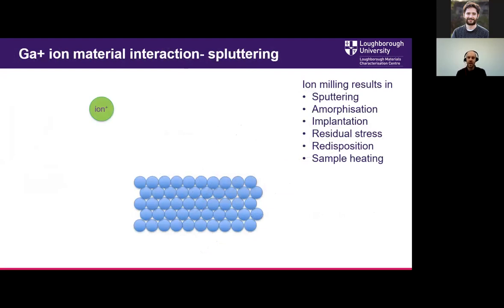So how does this ion milling system work? Essentially we have a billiard ball model, where we have an ion that's accelerated at the surface, hits the surface and sputters material away. You can think of this as billiard balls, or we sometimes say atomic jet washing. If you were jet washing your driveway, sometimes you clean the driveway and then you get some dirt hitting your windows. We would call that a redeposition.